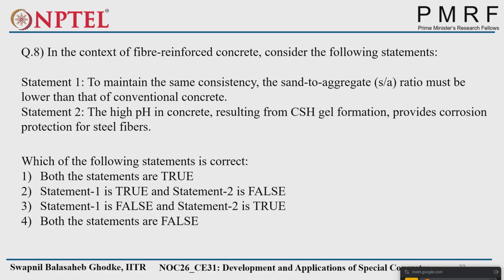The high pH in concrete resulting from CSH. The pH content is not resulting from CSH. It is resulting from CH, calcium hydroxide, that provides protection for steel fibers. CSH doesn't improve pH. Only CH content improves pH and other alkali content.